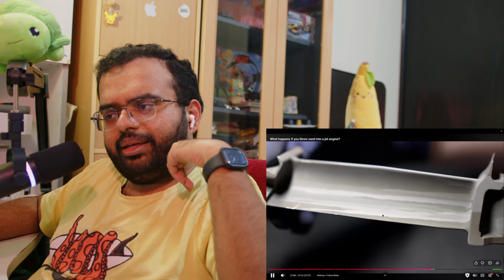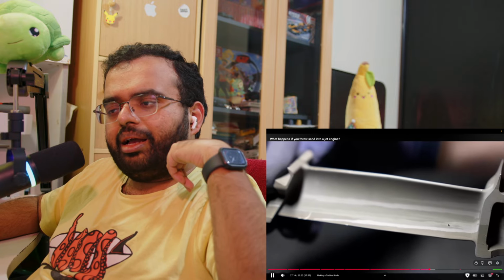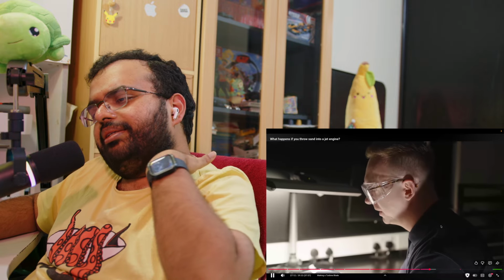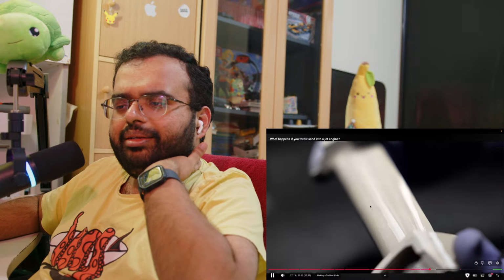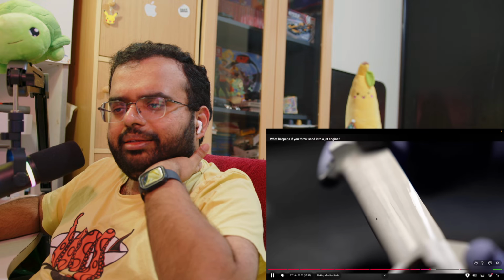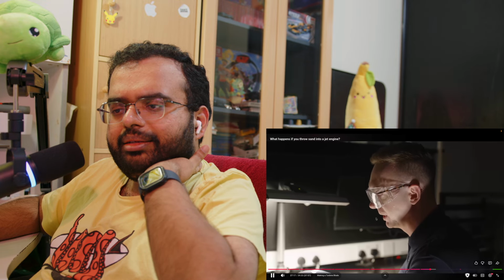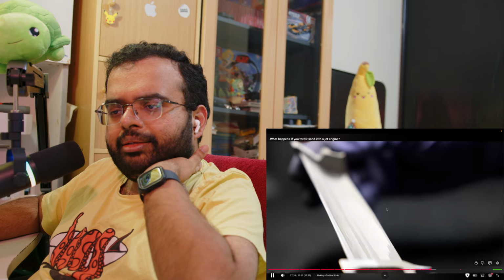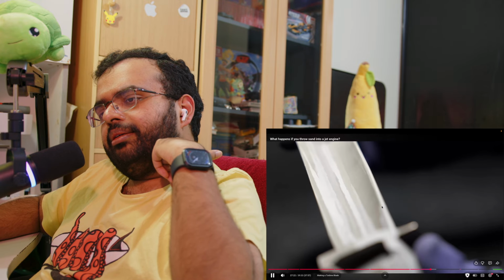Now, if we just did that on its own, you'd end up with a blade that looks like this. Here's a directionally solidified blade. And what you can probably see there is the contrast between the grains. These are all different crystals, but they're all running on this axis of the blade, which makes it significantly stronger than an alloy that is cast, where all of the crystals are separate from each other. So those are like individual crystals? These are individual crystals, yeah, absolutely.